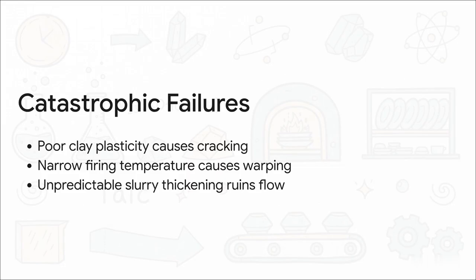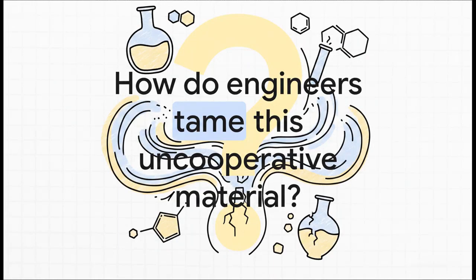First, the mud absolutely refuses to bend. It has terrible plasticity, meaning large pieces will literally just crack before they even dry. Second, the liquid slurry randomly thickens, kind of like a culinary emulsion gone horribly wrong, which destroys the flow stability you need for casting. And finally, the firing process in the kiln is incredibly unforgiving, leading to totally warped and deformed pieces. So it begs the question, how on earth do engineers actually tame this completely uncooperative material?